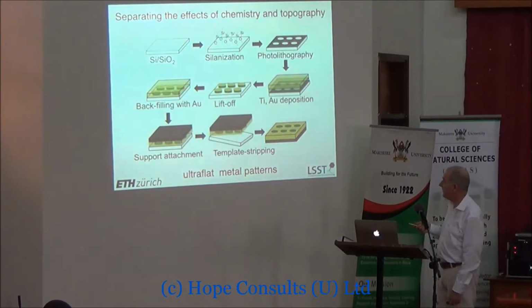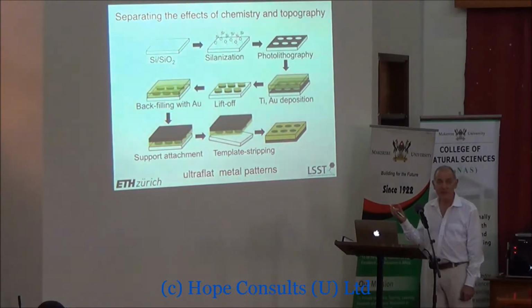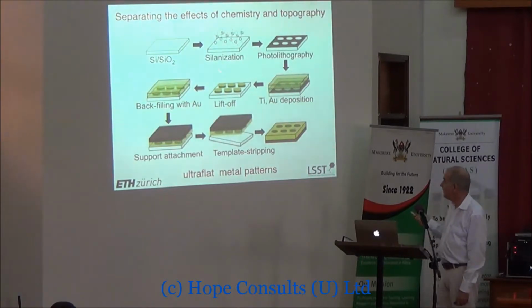The way we make ultra-flat metals is we start off with an ultra-flat surface, like a silicon wafer, which has an inherent flatness of around a nanometer. We silanize it. We silanize it because we don't want what we put on next to stick to it very, very well. Then we do photolithography to make a pattern of holes in the surface. And then we, first of all, we deposit some titanium through these holes onto the silicon surface. And then we deposit some gold on top of that titanium. And then we deposit more gold to fill in all of the gaps here. And so we now have titanium covered with gold, and the whole thing's in the background of gold.